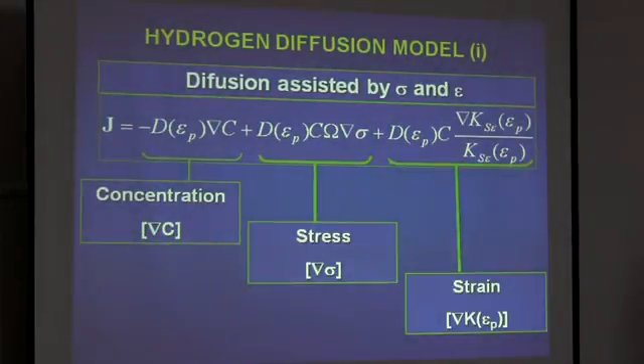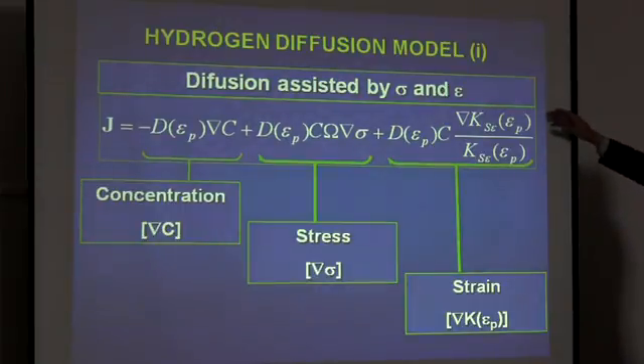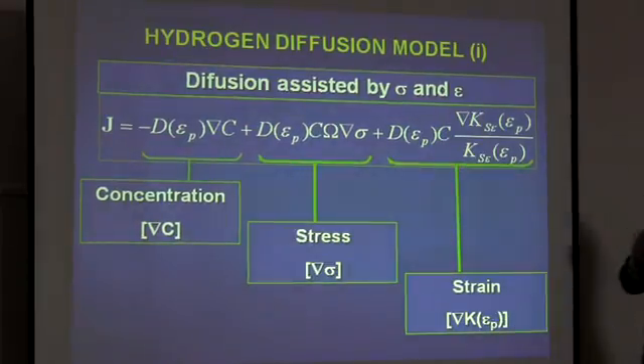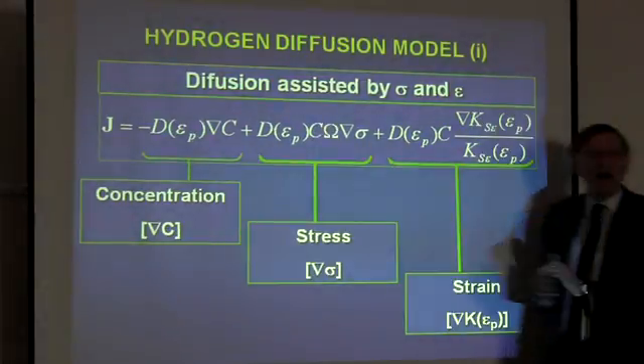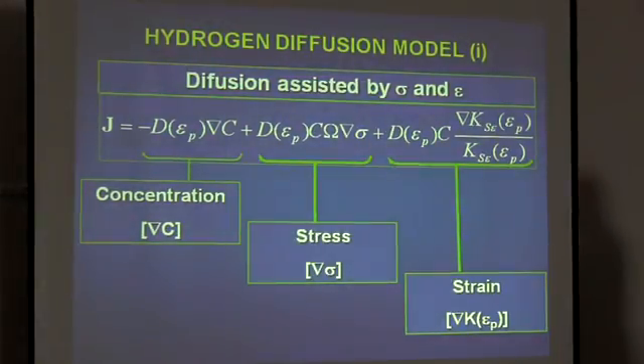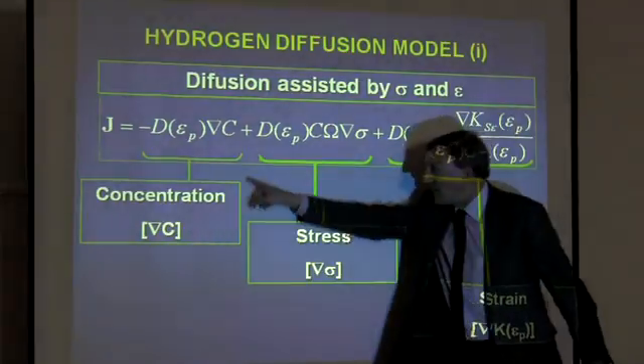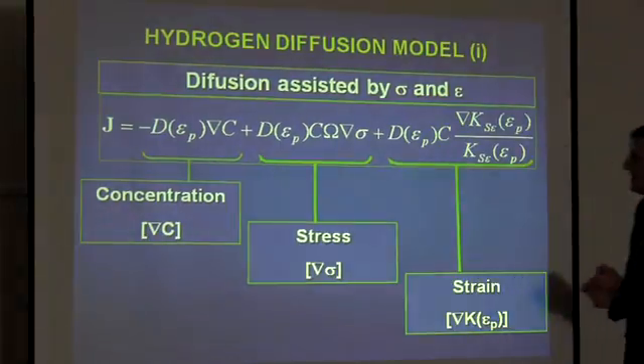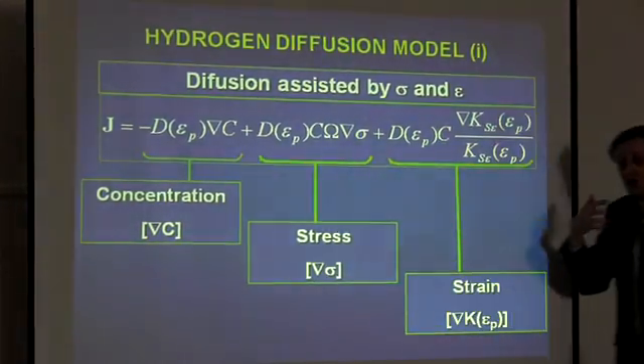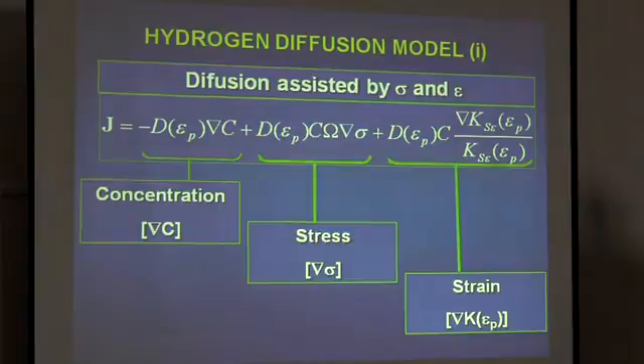Now, this is the equation for hydrogen diffusion, the hydrogen diffusion model. Diffusion assisted by stress and strain, in which the driving force, the hydrogen diffusion flux J, contains three terms. The term of concentration, the gradient of concentration, the typical Fick term: hydrogen diffuses as a function of the negative gradient of concentration towards the point where there is a scarcity of hydrogen, the typical Fick term.